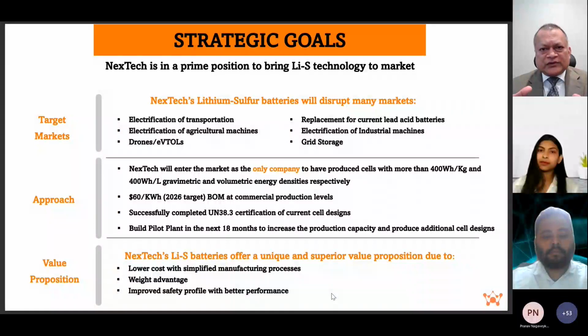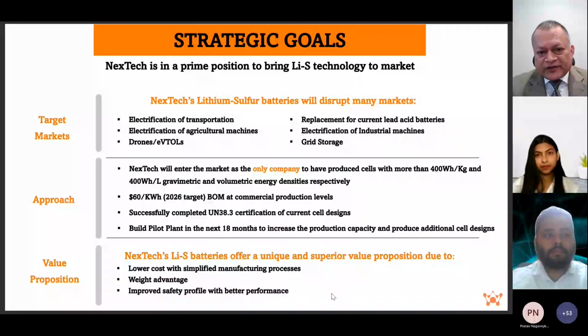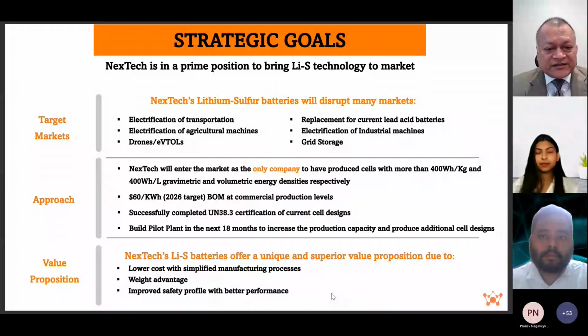Today we have to use excess lithium to balance and to provide for polysulfide formations. But if I can mitigate and eliminate the polysulfide formation, I can reduce the amount of lithium I'm using. And also, depending on how we synthesize the sulfur in the cathode active material, we may be able to reduce that $60 by another 1/4. So you're potentially looking at $45 to $50 easily, depending on how the research progresses.